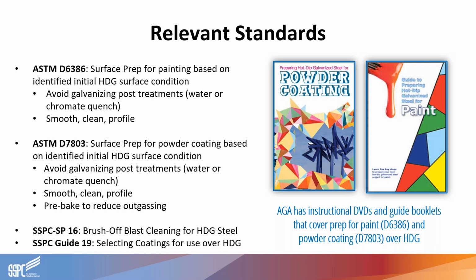Referenced within both standards is a specification for sweep blasting to profile the hot dip galvanized surface. That is SSPC SP16, which is brush-off blast cleaning for non-ferrous surfaces. This abrasive blast cleaning standard is the most common practice for cleaning and profiling the hot dip galvanized surface, and it includes specific steps to help avoid damaging the coating.